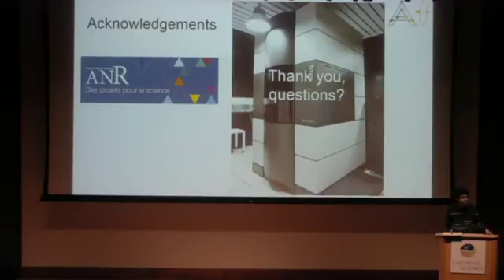You had a question? Yeah, I was curious as to whether or not you have any sort of in situ characterization during your PLD growth, and kind of, you have this changing of symmetry layer by layer. We have RHEED, but we don't really see it because I think the lattice parameters are kind of similar. Oh, but it's a big rotation, right? Oh, when it rotates. Okay, I didn't do the growth, so I should. That's a good question. Might be interesting to see whether it's templating out as the tetragonal phase or if it's forming after the fact. Yeah, that's a good question.